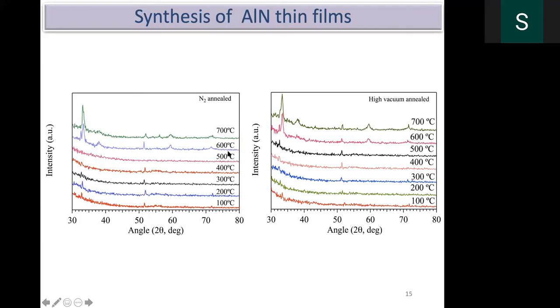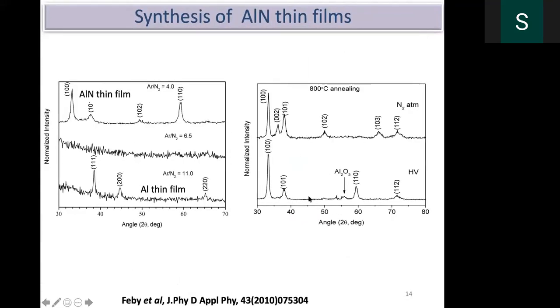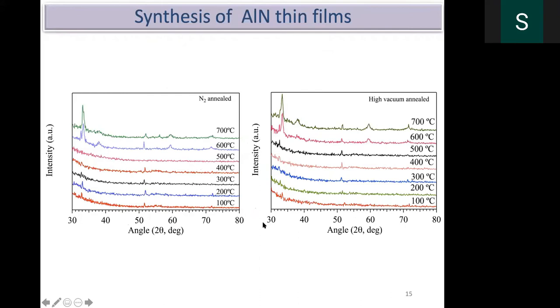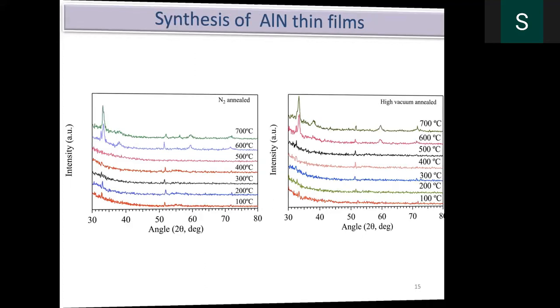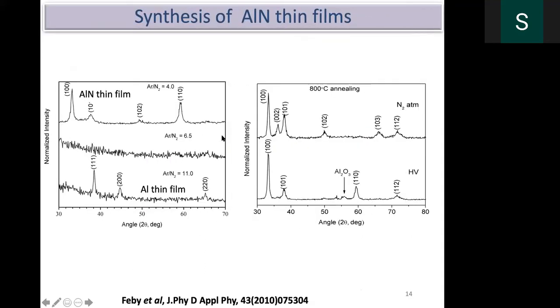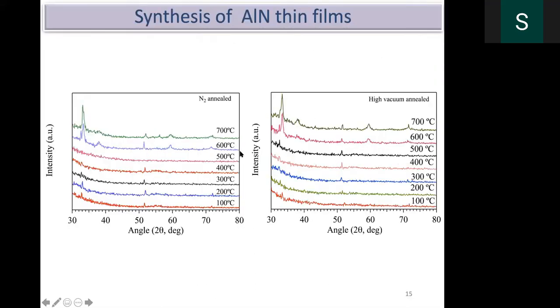But the moment you touch 600 and if you go to 700, the peak forms. Now you look at this, very clear peaks formed in the case of 800 degrees centigrade annealing. That's what we did, a systematic annealing in the case of amorphous aluminum nitride. That is around, if you see, argon to nitrogen of 6.5. And this has been published in the Journal of Applied Physics. One can refer to that.